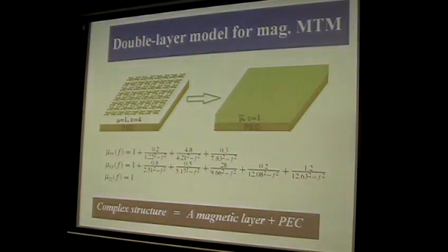And also, in fact, we found that this complex structure can be modeled by another effective medium model. Note that for this structure, we cannot use a single layer of effective material to characterize it. We have to use a double layer. We found that this structure, although it's very complicated, can be modeled by a double layer effective medium model, which is a homogeneous magnetic material put on the top of a PEC layer, the metal layer. And the mu tensor is given by this form. And we found that this model describes all the properties of these complex structures very well.